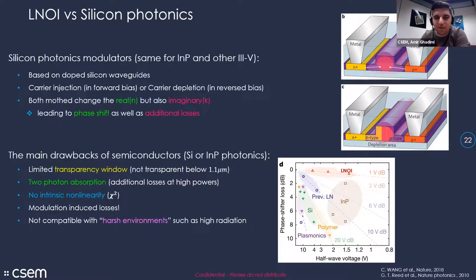And if these advantages are not good enough, add on top of this that we have a much wider transparency window, and we can operate below 1.1 micrometer. We can put a lot more power, so you don't have the two-photon absorption issue. In the case of silicon, we don't have an intrinsic Chi2, so you cannot do all these interesting nonlinear effects. And on top of it, this is a dielectric by nature, so it's intrinsically more resistant to harsh environments. That's why, for example, ESA is one of our biggest supporters, because they want to deploy this technology in space where you have a lot of radiation. So dielectrics are more resilient.